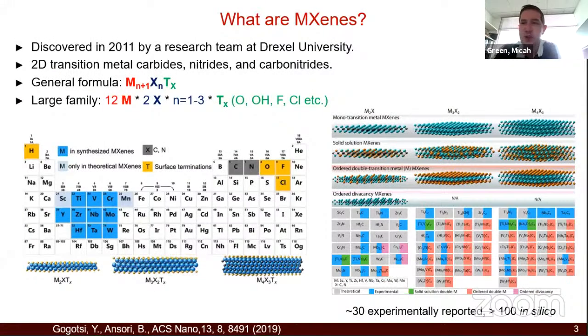So if you've never heard of MXenes, you can think of them kind of like the ceramic equivalent of graphene. The idea is that the M is usually a metal. Titanium is the most common one, but there's lots of them, you know, niobium, vanadium, chromium, things like that. And then the X is either carbon or nitrogen. Usually it's carbon, but people have done a lot with nitrides as well. And then you'll also see people use this T designation. The T just means that these are planar 2D structures, M, X, M, et cetera, or M, X, M, X, like so. And then there are terminal groups. That's what the T is. There are terminal groups, which are functional groups that allow these things to be water dispersible. So that's why people are so interested in these. They're two-dimensional ceramic nanosheets, and they're typically water dispersible, and they have lots of exciting properties.